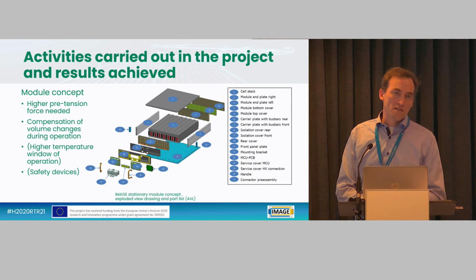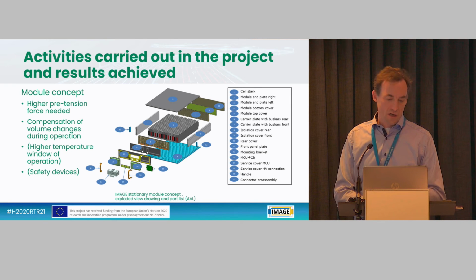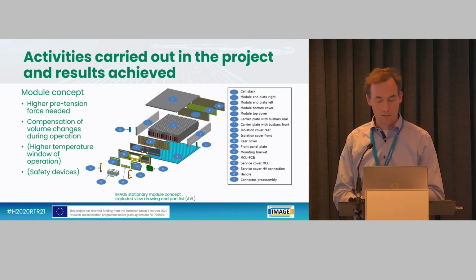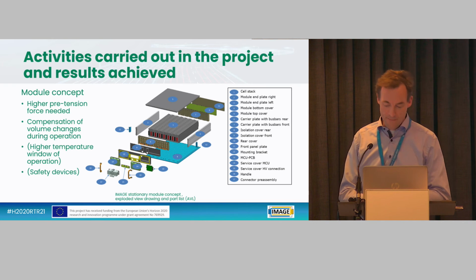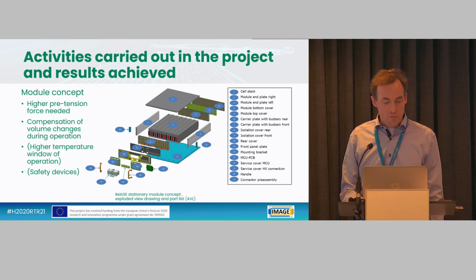We found out with the results from the first monolayer cells that it is possible to go with a rather conventional module concept. We were discussing already pneumatic systems or hydraulic systems for applying a defined pretension force. It showed up that with compression pads which are under development at the moment, it's also possible to buffer away the volume changes and to apply the higher pretension force needed for the gel polymer electrolyte cells. So this was based on the cell testing.